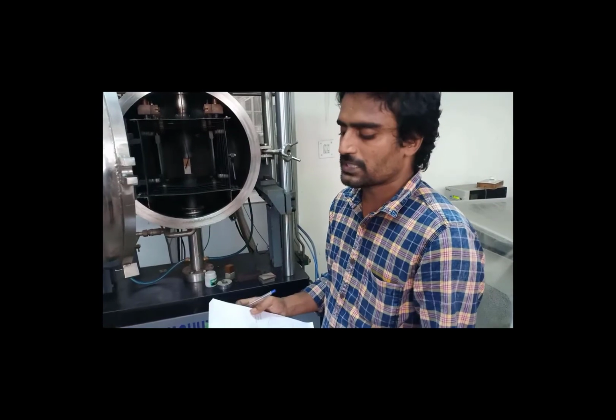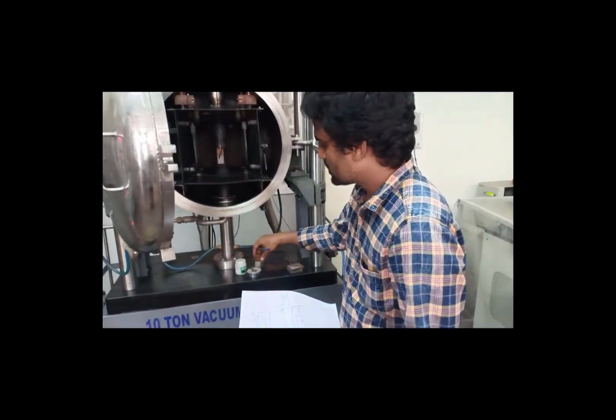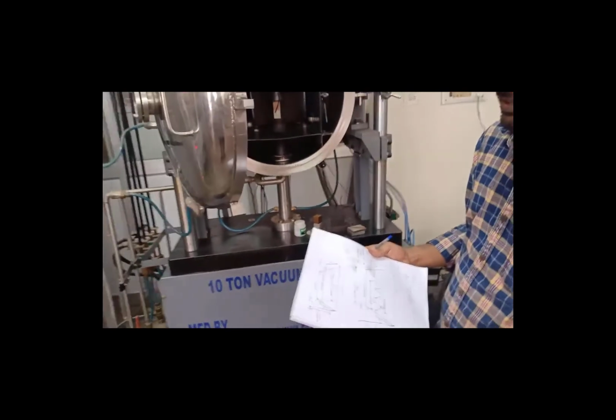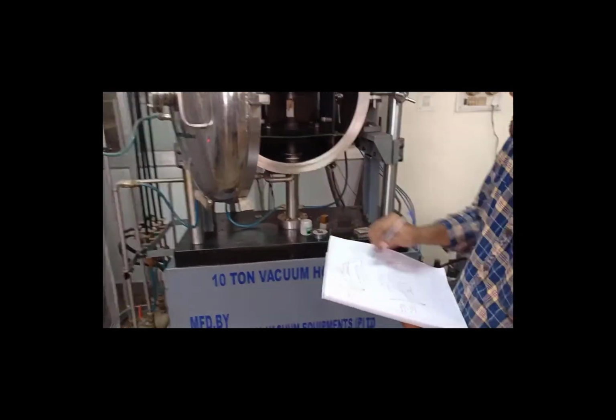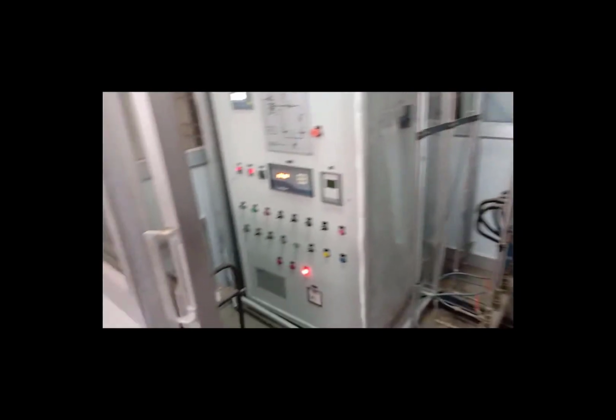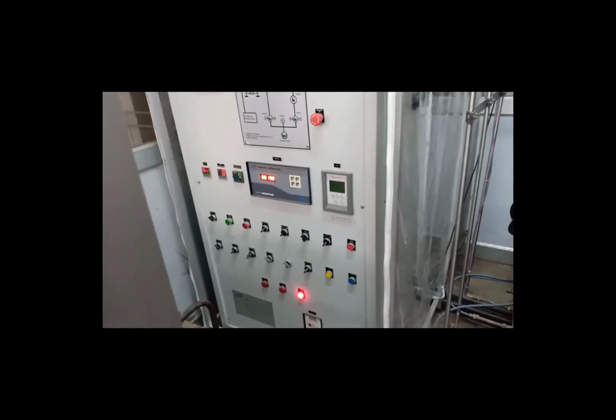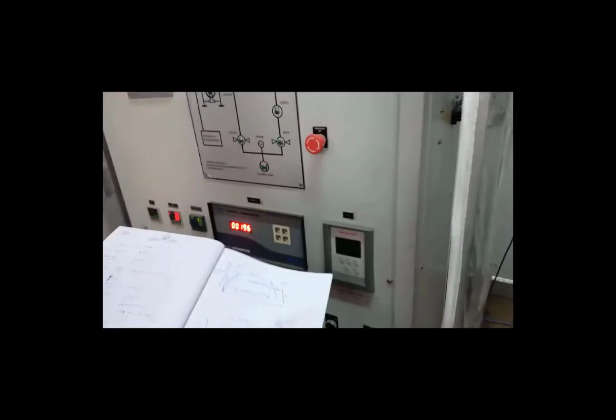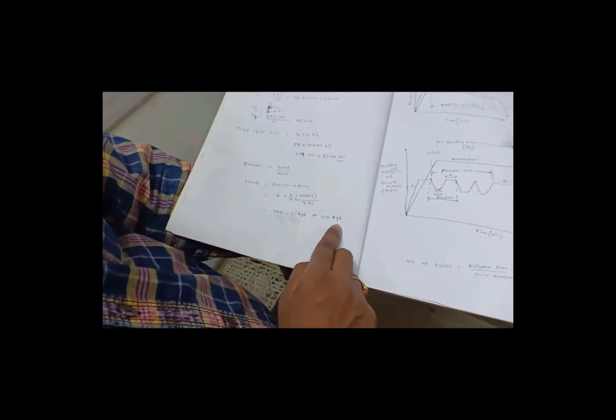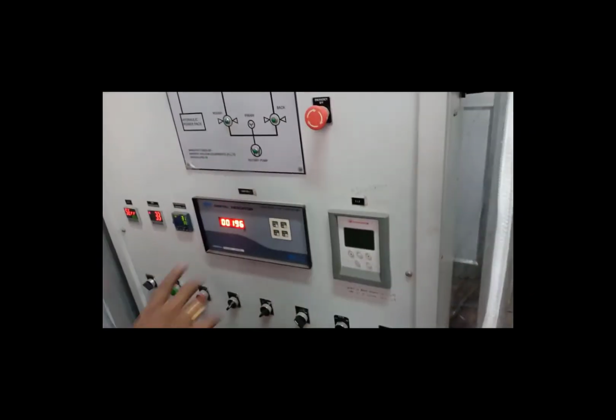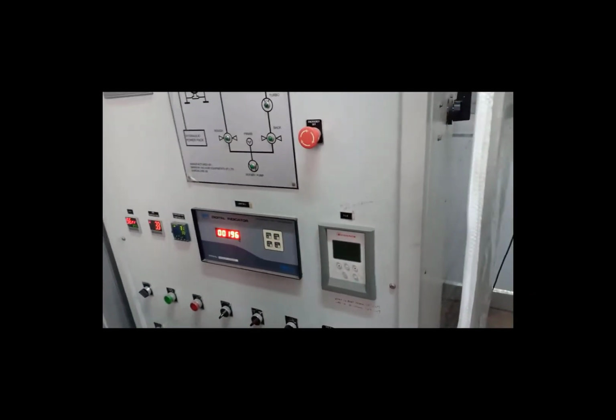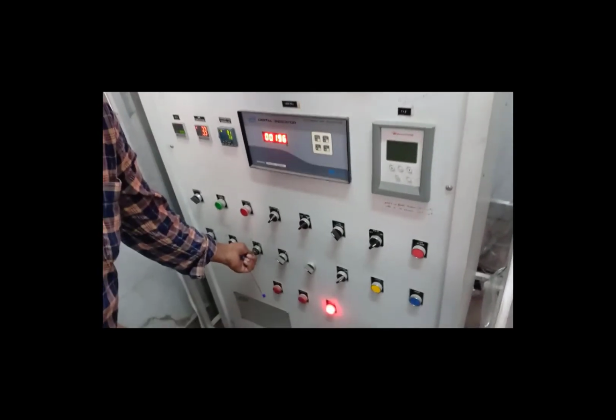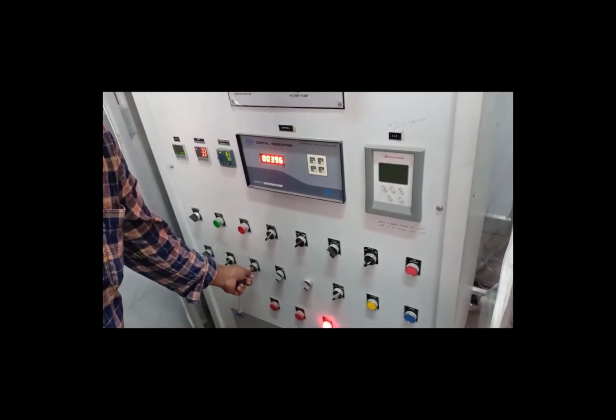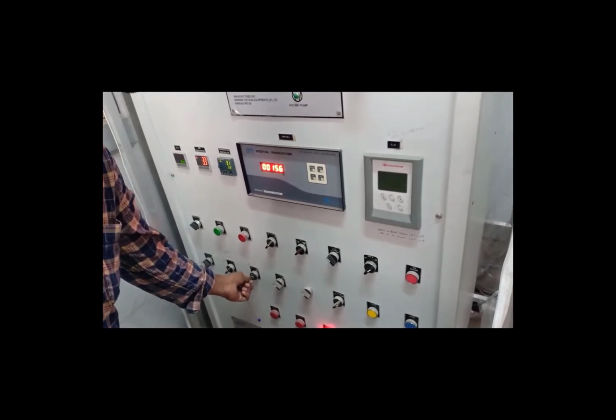So we'll perform the basic operation now, with stainless steel and copper. We are not going for the pulsation here. These parameters we need to set in the control panel. Before that, the load cell is showing the load. How much load we have to apply here is 300 kgf, kilogram force. For that purpose, the sample is loaded, and the first step is to adjust the load accordingly to 300. It has gone to 396, so we will reduce it.